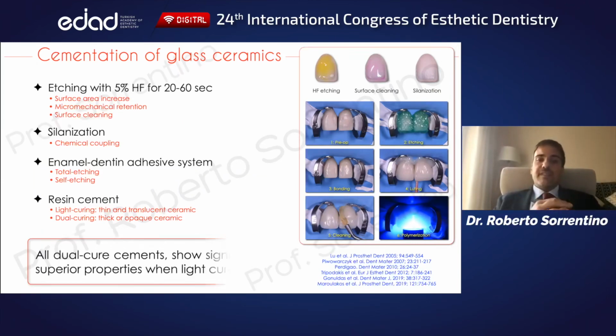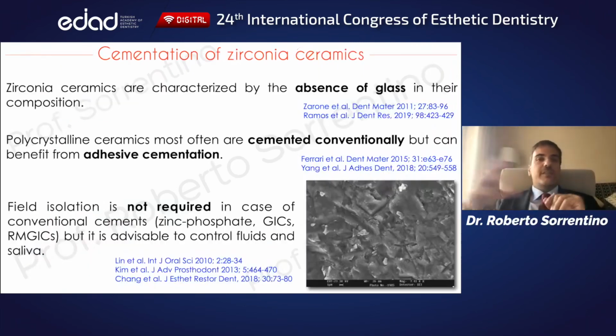It is worth noticing that the properties and performance of dual cured cements are much better if they are light activated. So always initiate the chemical reaction with a few seconds of photopolymerization. Vice versa, zirconia is a silica-free ceramic metal oxide and should be cemented with conventional or resin-modified glass ionomer luting agents. Simplified resin cements can be used in cases where we want to improve a not satisfactory retentive geometry by means of a kind of active chemical adhesion.